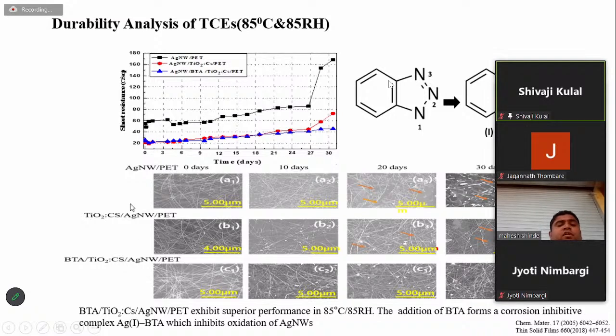But with only the TiO2 CS, there is also oxidation of the silver nanowire after the 30 days. But with the BTA, after the 30 days we can see uniformly distributed silver nanowire, which proves that applying BTA, a corrosion inhibitor, provides protection to the silver nanowire in harsh environmental conditions, such as 85 degrees Celsius and 85% RH.